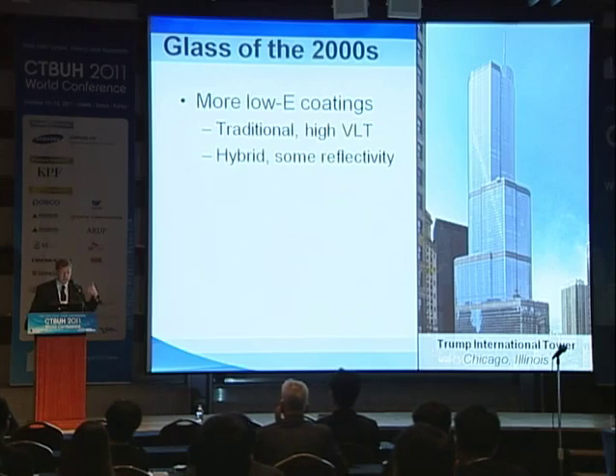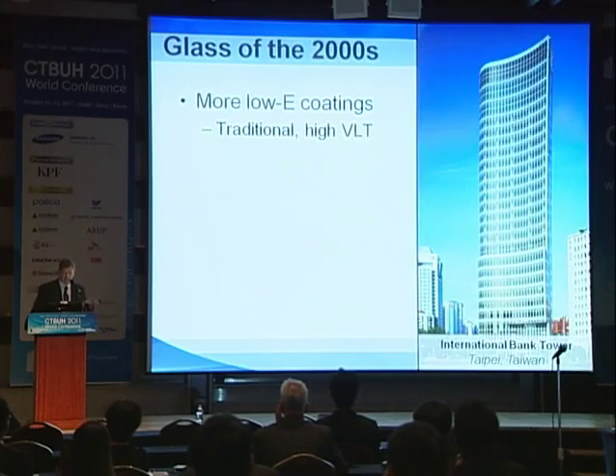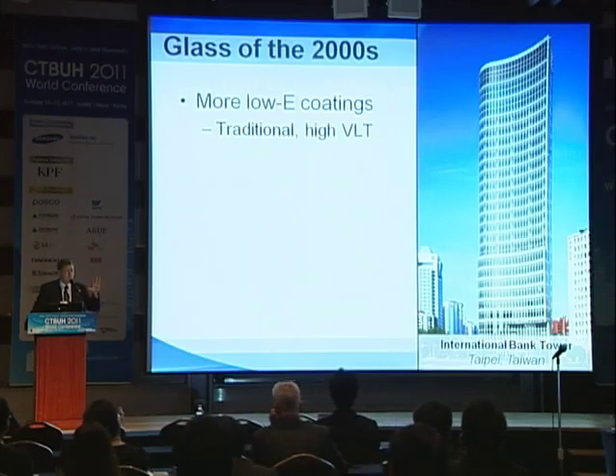If we can go back to one of the slides, you can see the low emissivity coatings are very, very transparent. And again, in certain applications, if you don't have direct sunlight on them, they go very dark. They go kind of black. And that's when we start talking about reflected versus transmitted conditions. So again, when you're looking at high performance reflective coatings, they tend to have that shininess and appearance. When you're talking about low emissivity coatings, they are anti-reflective coatings in nature.